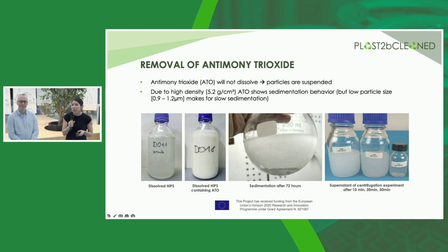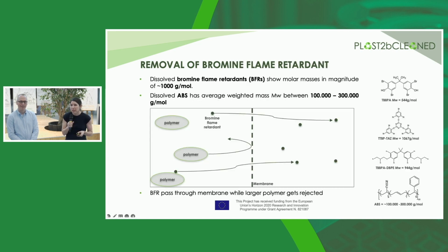And after sedimentation, that took about 3 days, so 72 hours, you can see the ATO particles predominantly sedimented at the bottom of the flask. There is still some discoloration of the solution, so it's not fully separated, but the majority of the ATO will sediment. And on the right-hand side picture, you can see the results of the centrifugation experiments after 10, 30, and 50 minutes. You can see that with increased time, the ATO can be fully separated and found at the bottom of the flask.